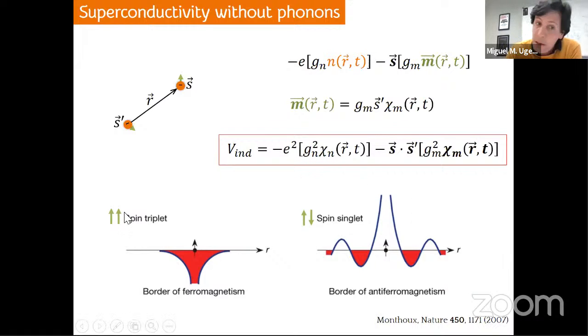So basically, for example, in the vicinity of ferromagnetism, spin triplet configurations are favored, okay? And given the sign of this material, it can be demonstrated that the magnetic susceptibility is maximum at the origin and decays monotonically with the distance, yielding an attractive interaction in this second term. So this is the effective potential interaction that this spin triplet configuration feels.